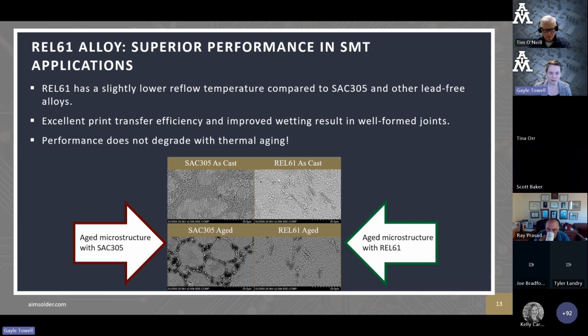The picture at the bottom here shows microstructure of SAC305 and REL61 when they're initially cast, and then after aging at that 150 Celsius for a day. What you see is the SAC305 forms all of these structures within it, and those can lead to paths for breakage and reduced structural integrity. REL61, in contrast, tends to maintain most of its structure even after the aging.